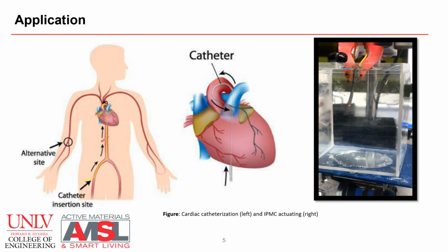For this study, we go through the electrochemical characterization of IPMC due to temperature. Many factors affect the dynamics of ion mobility in IPMC. The mean free path of ions, which is a factor of membrane thickness and the membrane's chemical and physical structures. Characteristics of ions, which follow the van der Waals volume, and temperature. While characteristics of the membrane and ions are intrinsic to IPMCs and are fixed, temperature is considered an external factor that can be changed.